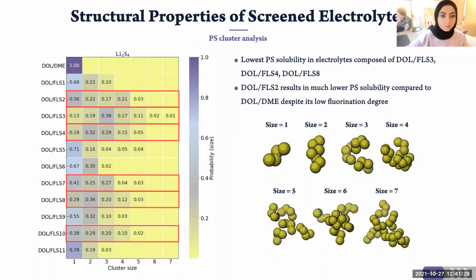of clustering forming. FLS4, if you remember, the one that was proposed in the literature and used extensively, we can see that there are solvents that are leading to much higher degree of clustering and lower solubility of the polysulfides compared to these solvents.